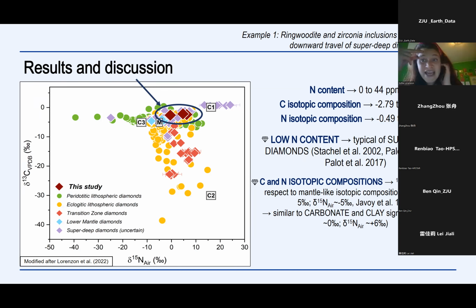The fact that our diamond has a low nitrogen content suggests that probably this is a super deep diamond. In fact, typically super deep diamonds do not contain nitrogen or have a very low nitrogen content, as in this case. And the carbon and nitrogen isotopic compositions, on the other hand, are not similar to the isotopic compositions of the Earth's mantle, but are similar to the carbon and nitrogen isotopic compositions of the carbonates and the clay minerals that are present in sediments. And for these reasons, we suppose that probably our diamond is a super deep diamond precipitated from a fluid or a melt with a slab-derived origin.